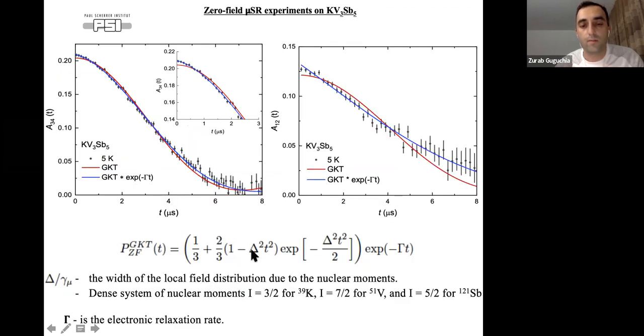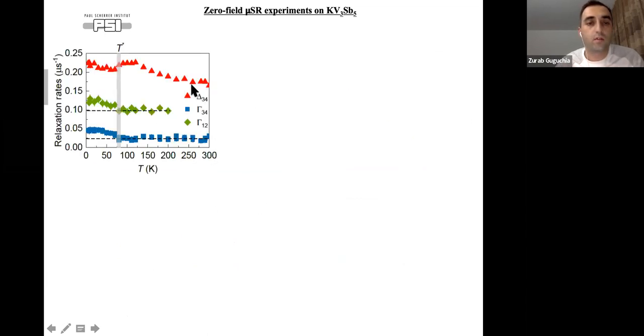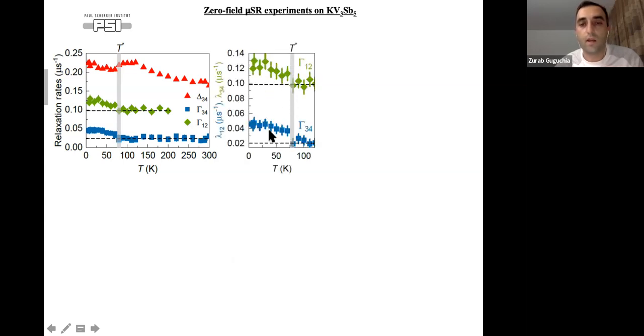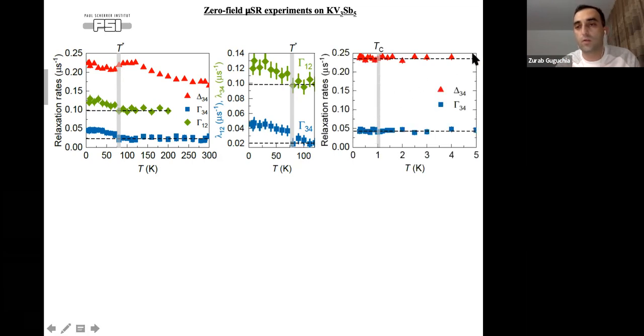So if I now plot delta, which is the width of the local field distribution, as a function of temperature, together with the exponential relaxation rate, this is what we get. You clearly have an increase of the exponential relaxation rate below the charge density wave transition temperature, which you can see more clearly here. This increase of the relaxation rate means that you have an enhanced spread of the internal field distribution at the muon site just below the charge density wave transition. And then it continues at low temperatures, and across Tc we don't see much change. So it really continues into the superconducting transition.